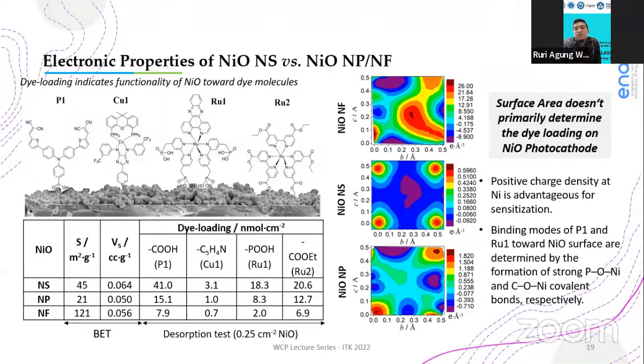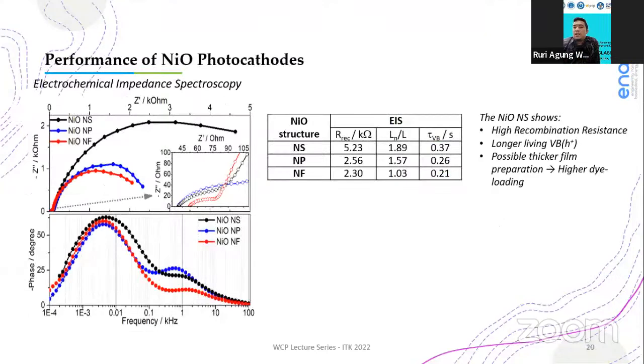So here we find that the electronic properties of nickel oxide nanostars is favorable for dye sensitization, because from the electronic nature of the nickel oxide nanostars, the positive charge density at nickel atoms could facilitate the covalent bonding with the carboxylic acid or phosphonic acid anchoring group from the dyes. And this is further confirmed from the performance of the nickel oxide photocathode itself, involving electrochemical impedance spectroscopy and also current voltage measurement. The impedance analysis indicates that nickel oxide nanostars has the highest recombination resistance compared to the other structures, as well as the longest living valence band hole lifetime, which is extracted from the electrochemical parameters after fitting.